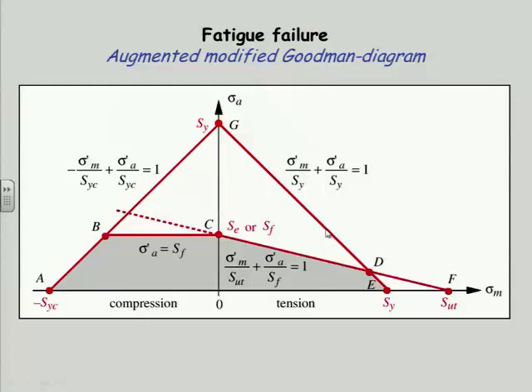So this is what I use and what I propose to you as a good solution. I've extended the line so you can see the SY just ends up at SY up on this axis. That's my breakout point for static loading in essence. The data shows that it continues more or less at the same slope back into the compressive regime, but we, being conservative, say we'll just level that off. And we could have yielding in the compressive direction as well. So that puts a limit there. And here's our Goodman line going off to SUT from the endurance or fatigue strength. So the gray area is our safe zone.